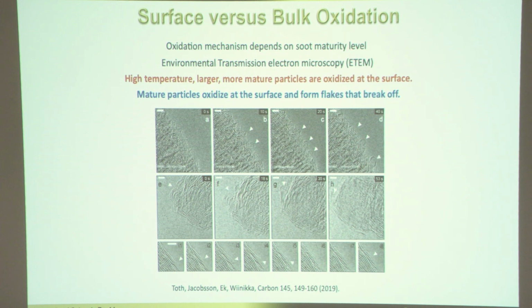And it's probably a matter of the oxygen being able to filter into the center of the particle and get to the more reactive part of the particle. And if the particle is big, it's probably harder for the oxygen to get in, but it takes a higher temperature to oxidize these more mature sheets of graphene. So I think that's actually really cool. And so you see on the upper right-hand side, what they see is you probably pull off individual oxygens, and you start to flake off parts of your graphene sheets, your polycrystalline graphite sheets.